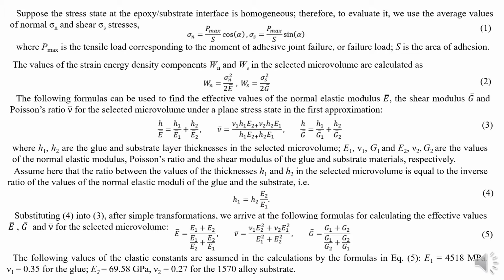Suppose the stress state at the epoxy substrate interface is homogeneous. Therefore, to evaluate it, we use the average values of normal sigma and shear sigma as stresses. In Formula 1, Pmax is the tensile load corresponding to the moment of adhesive joint failure, or failure load. S is the area of adhesion.